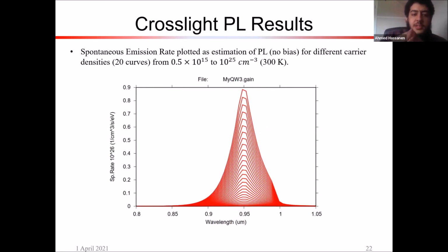And so the next step was to then do some modeling of the spontaneous emission rate as an estimation of the photoluminescence. And this is just room temperature photoluminescence, 300 Kelvin, in the simulation. And I did this at different carrier densities, from 10 to the 15 all the way to 10 to the 25. And you can see as the carrier density increased, the width increased. So this was just an interesting modeling scenario I made during COVID.